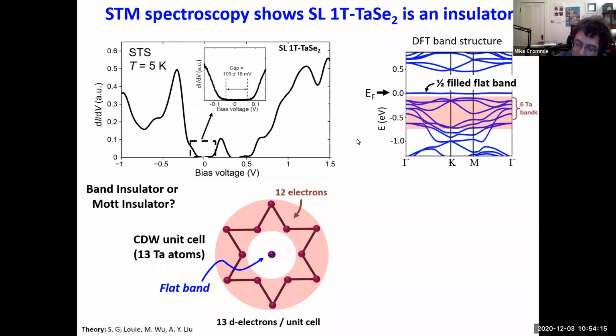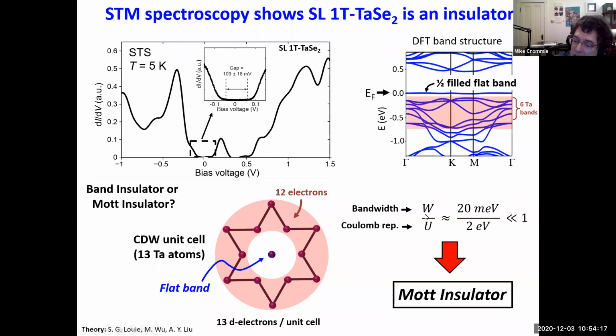But if you look at it a little closer, you'll notice that it's a very flat band. The width of that band is only on the order of 20 millielectron volts, whereas the U, the Coulomb repulsion that you expect in that band, is on the order of 2 electron volts. That means that this ratio is really tiny, much less than 1, on the order of 1/100. And so that means that correlation effects must be very important here. And so we expect this to be a Mott insulator. So that's strong evidence that this is a Mott insulator.